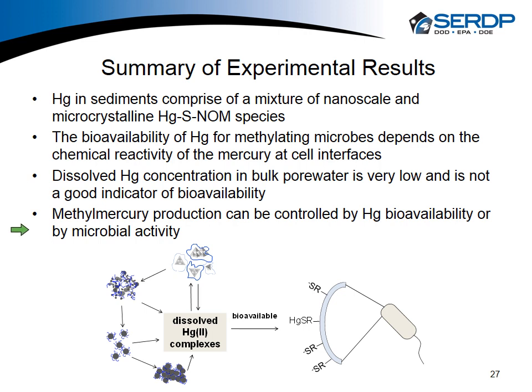And this last point comes from our sediment microcosm experiment, where we show that methylmercury production can be controlled by the bioavailability of the mercury, so the chemistry of the mercury, and it could be controlled simply by the activity of the methylating organisms. And there's a balance to be played here where one might be more important than the other in controlling methylmercury production.